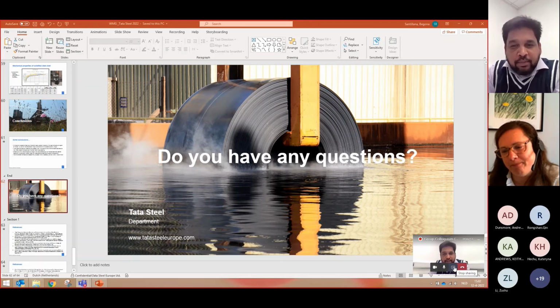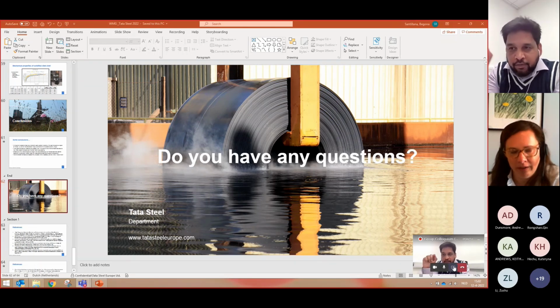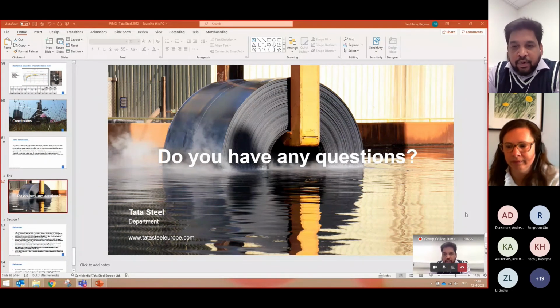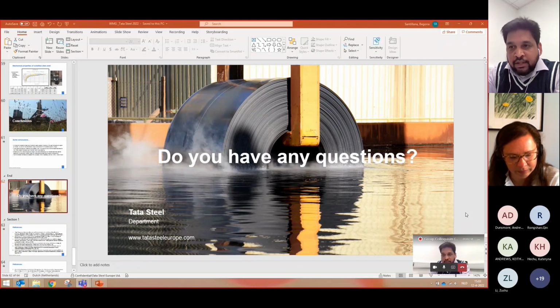When you mentioned this boron, when you add it, you see the liquid surrounding the grain boundaries. That could result in cracking. Did you observe any such kind of composition in a confocal, either cooling slowly to see whether the liquid is reappearing after solidification?